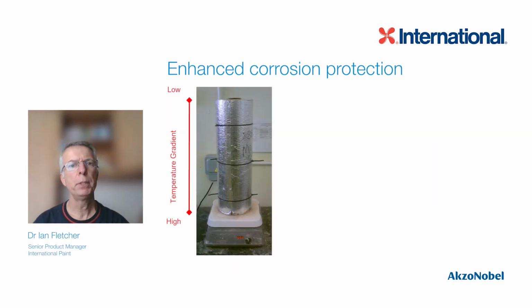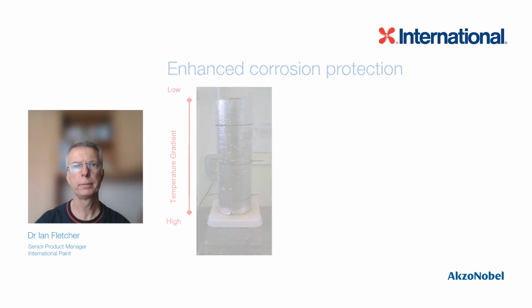Interbond 2340 UPC has been tested in the vertical pipe test, as described in the ISO 19277 standard, used to pre-qualify coatings for use under insulation. In this test, it was shown that 2340 UPC performed just as well, if not better, than traditional epoxy phenolics, with no coating defects observed up to 230 degrees Celsius.